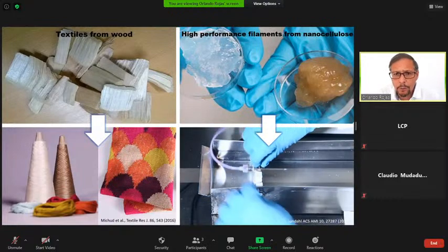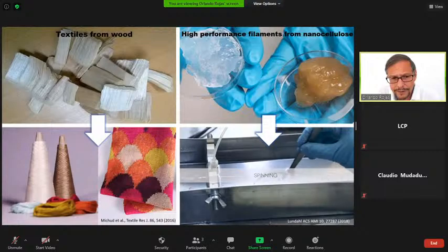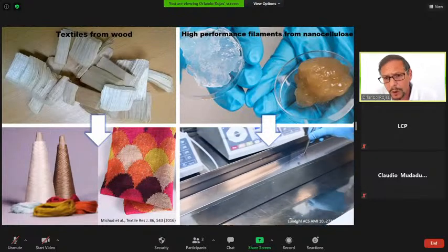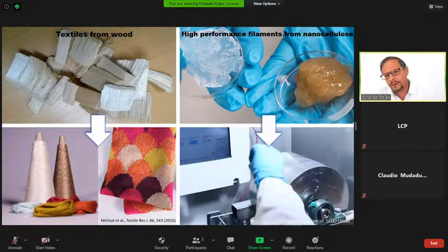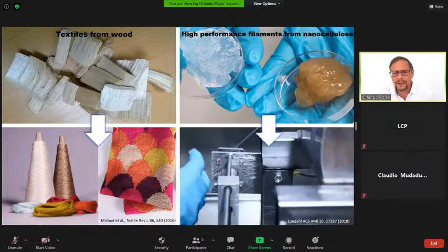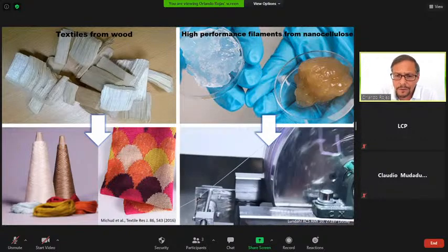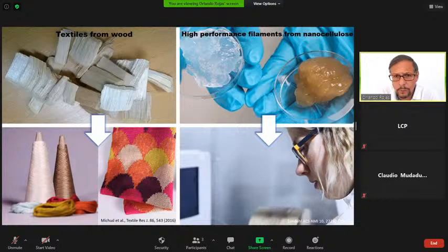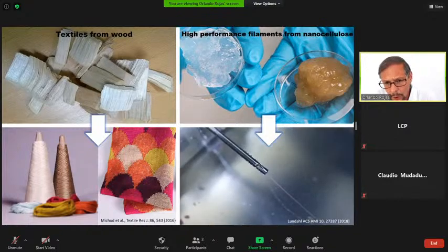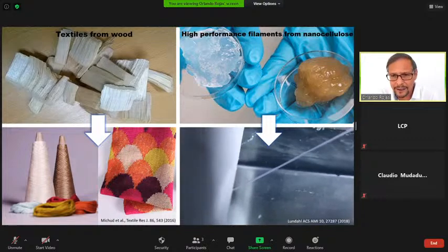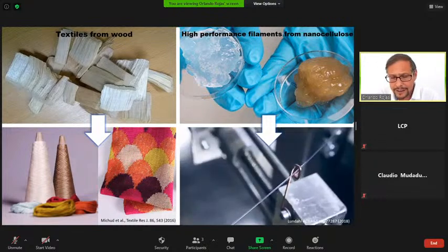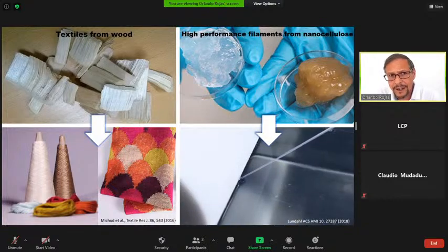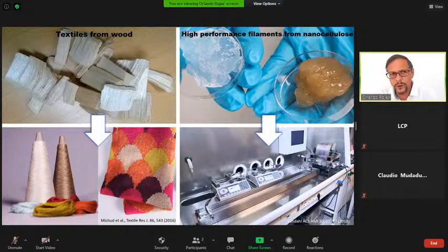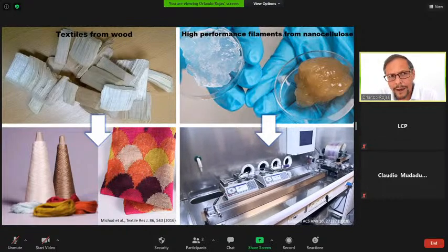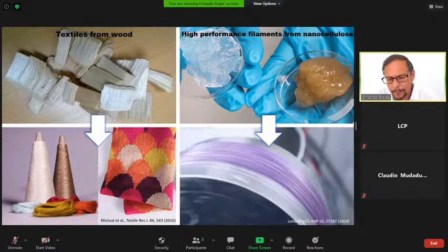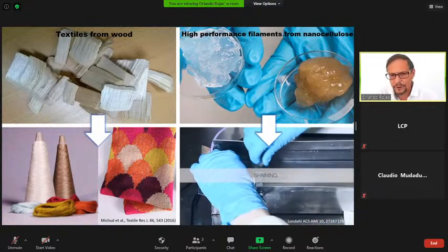For our own research in our group, we do similar efforts, but we don't use ionic liquids. We do, but in this context, I want to introduce more the use of nanocellulose that I introduced earlier, and I will give some examples. So the case of nanofibrillated cellulose free of lignin, and also nanofibrillated cellulose containing lignin, which you see on the top right as an example. And I like the case of lignin-containing nanocellulose, since I think there are huge opportunities in this area, even though relatively speaking not many papers exist on lignin-containing nanocellulose.